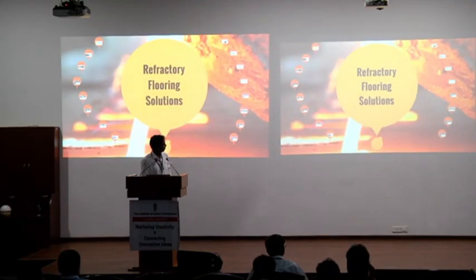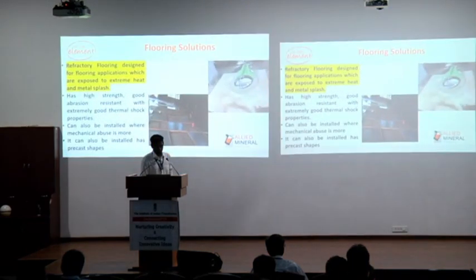So this is with respect to flooring solutions. We have a product called Tough Floor, which we normally recommend for flooring solutions in the foundry industry. This is an alumina silica based refractory. We engage wherever the standard concrete is exposed to a large amount of heat and metal splashes. This product is designed with good abrasion resistance and resistance to thermal shock with high strength. It is mostly installed as cast in place, but we can also do precast shapes with this product.